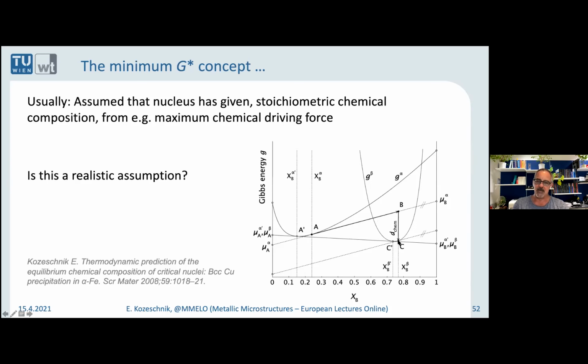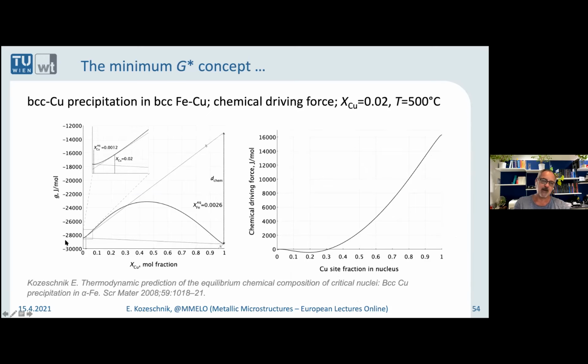Once you do that for the iron copper system, you arrive at the Gibbs energy diagram that looks like this one here. So you have a very low solubility range on the edges of the system, 1 or 2% solubility on either side, and all the mixtures in between are not favorable. So in equilibrium, you will always have a complete decomposition into iron-rich particles and copper-rich particles. But computational thermodynamics does allow us to still evaluate the driving force for any composition that we can imagine. And this is done here on the right diagram.